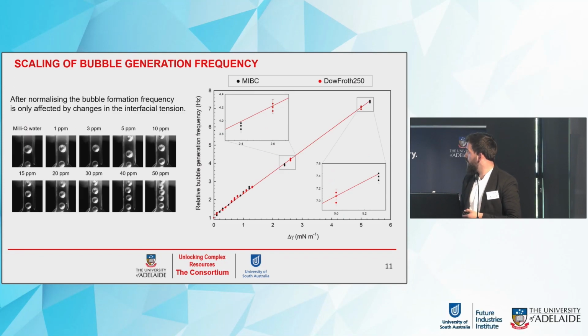And finally, we can normalize the bubble generation frequency with respect to water at a given flow rate to receive this relative bubble generation frequency and plot that against the drop in interfacial tension. And after this scaling, the data of relative bubble generation frequency for both floaters, MIBC and DowFroth250, and all different considered flow rates can be fitted into one straight line, showing that relative bubble generation frequency is independent of continuous phase flow rate, and it's only affected by the changes in interfacial tension, which means that this method can be used in different process environments, let's say where we use salt water or different process water, as we can always introduce this bubble formation frequency scaling by the value for process water.